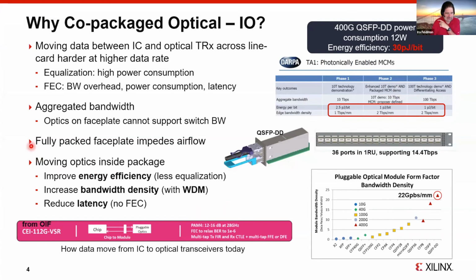Thank you. So basically, to summarize the motivation for co-packaged optics, the problem we're trying to address really is threefold. One is to improve energy efficiency dramatically. Even if we don't hit this 2.5 picojoule or 1 picojoule per bit target, if we hit like 4 or 5 picojoule per bit, that's still close to tenfold improvement compared to the state of the art today. And the bandwidth density improvement will have to rely on a technology called WDM. Basically, optically, you can put multiple optical channels on a single fiber. That's going to dramatically increase the edge bandwidth density.